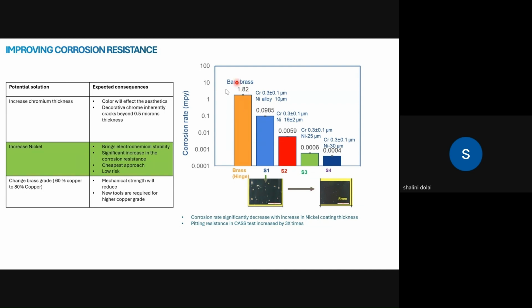So we studied it. We took bare brass. By keeping all other coating thicknesses the same, we just varied the nickel alloy thickness, and we found a dramatic reduction in the corrosion rate, almost by 1,000 times, and the pitting corrosion reduced significantly. So this was one of the approaches.